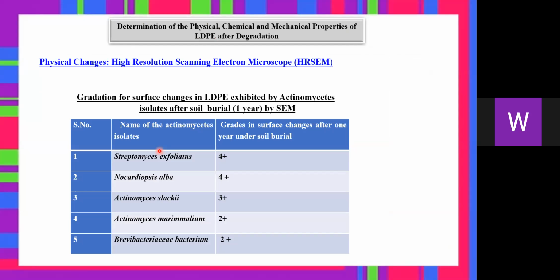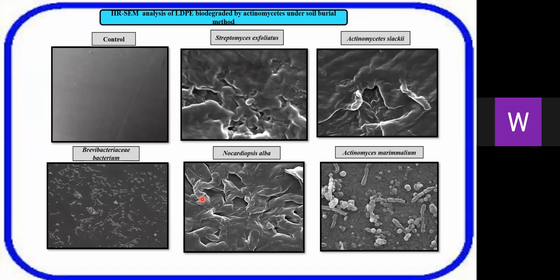Next, determination of physical, chemical, and mechanical changes after the soil burial study. Physical changes by HRSEM, and the gradation was given as 4+, 3+, and 2+. 4+ indicates the excellent surface changes exhibited by Streptomyces exfoliatus and Nocardiopsis alba, followed by slacki. This slide shows the SEM analysis of LDPE degraded by actinomycetes in the soil burial method. Compared to control, all 5 actinomycete strains have shown great surface changes by formation of grooves, holes, pits, roughening of the polymer surface, and complete erosion because of the degradation.